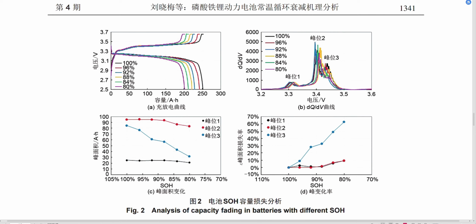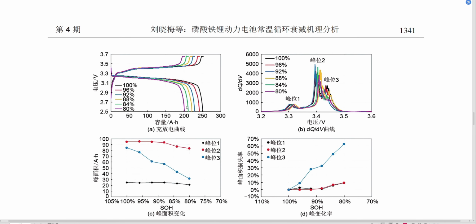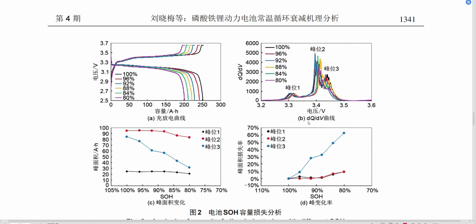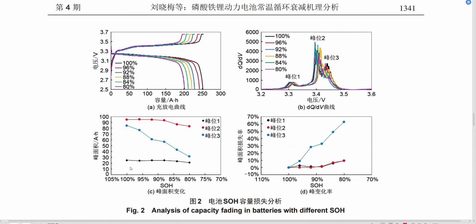So in Figure 2D, that is the peak area loss rate versus SOH for different peaks. So it's basically transferring this value to the percentage of the loss. You will see in Figure 2b, the QDV curve, the 3 peaks have some shifting, and also in Figure 2c, you will see the peak area has some changes.